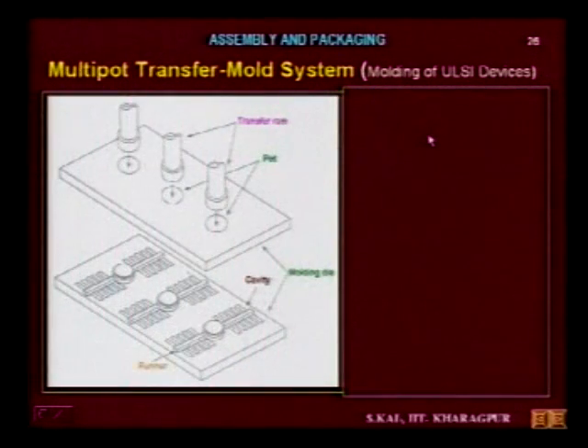Now, the multi-pot transfer mold system. In this molding process, we can directly mold the package chips with the lead. Thermoset molding materials, that is epoxy compounds, are usually transfer molded in large multi-cavity molds. After it enters the pot, the molding compound is usually preheated, melts under pressure and heat, and flows to the mold cavities containing lead frame strips. These are lead frame strips with their attached chips.